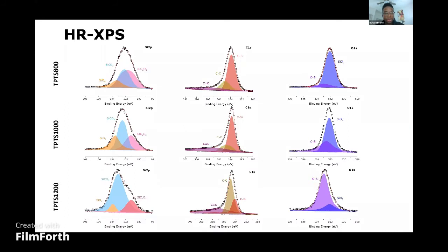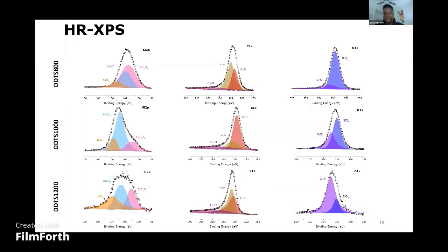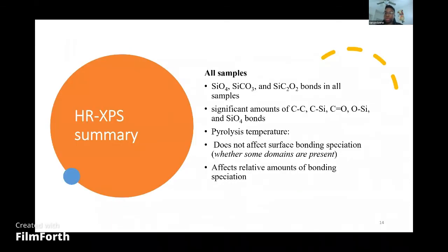Similarly, we further investigated the surface microstructure of these materials by performing high-resolution XPS in order to identify the bonding speciation from their Si2p, C1s, as well as O1s deconvolutions. And we did this for both TPTS and DDTS-derived ceramics. From our results, we're able to see that in all samples, independent of the polymer precursor that was utilized, we do see significant amounts of bonds corresponding to SiO4, SiCO3, as well as SiC2O2.